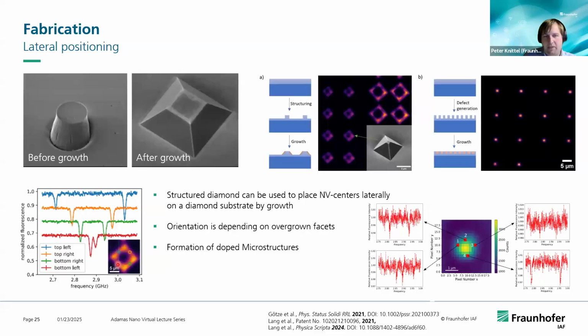Depending on where you measure, you get the signal from the NV center and how strongly it feels the magnetic field that is applied. Apparently the blue measurement point here sees the highest impact of the magnetic field gradient that is applied, whereas the red has almost no interaction with the magnetic field. So this again gives you an idea of the full vectorial components of the magnetic field.